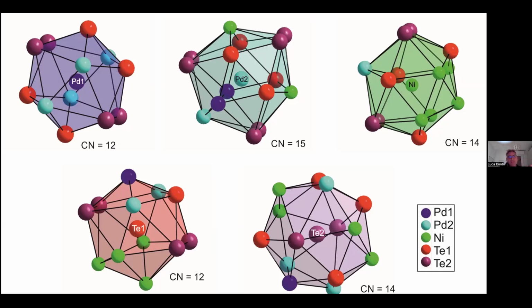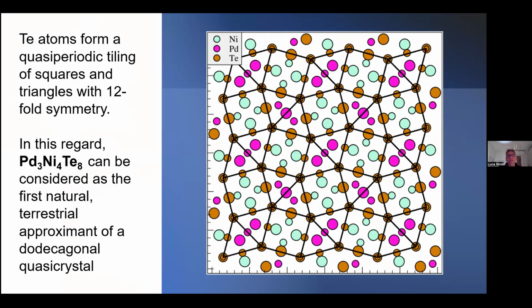if you plot the structures and you look at the tellurium distributions, you can see that they are distributed along a classic dodecagonal distribution. So you have structural features typical of dodecagonal quasicrystals, but we are still periodic. The new mineral has been approved by the International Mineralogical Association with the name proxy-12-foldite, because of course it approximates a possible quasicrystal which could be named 12-foldite, in analogy with icosahedrite and decagonite, the first with icosahedral symmetry and the second with, of course, the decagonal symmetry.